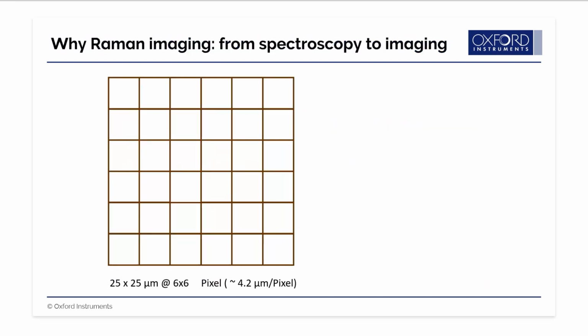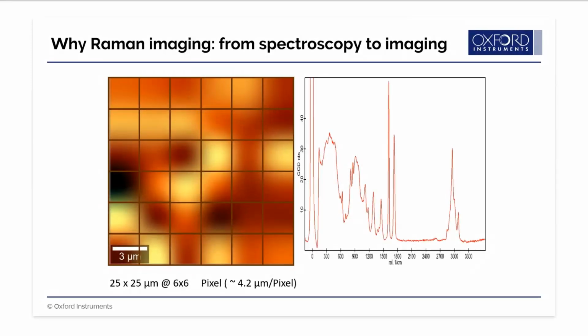Why high-resolution Raman imaging? Let's consider a polymer blend where we measure an area of 25 by 25 micrometer square with 6 times 6 pixels and long integration time per pixel. The image and spectra we obtain look like this. Now we increase the number of pixels and decrease the integration time per pixel to keep the total image acquisition time the same. Look what happens.